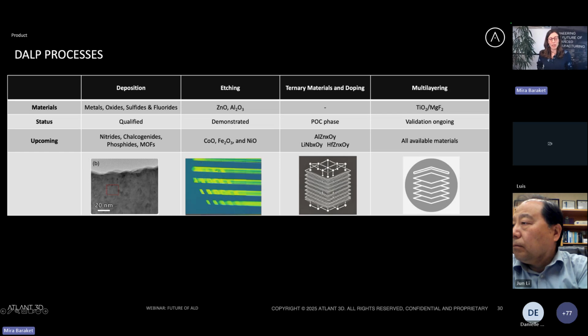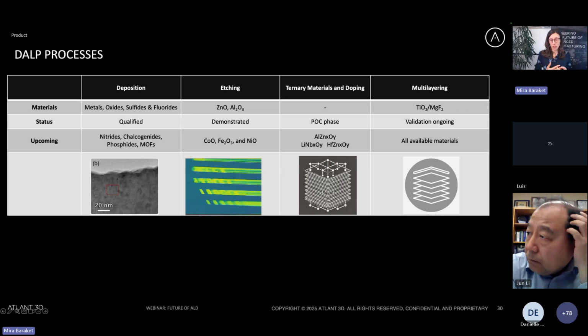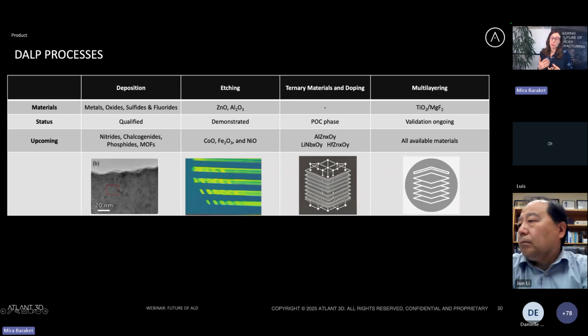Also on the etching side, we have confirmed and demonstrated etching of zinc oxide and aluminum oxide, and more are to come soon. We are in the proof of concept phase for making ternary materials, and we are interested in the materials that are listed here: aluminum zinc oxide, lithium niobium oxide, and hafnium zinc oxide. Multi-layering, of course, is inherent to our technology. So it is something that we can do with all available materials. We have already validated titanium oxide and magnesium fluoride, and also we've validated more materials that are based on aluminum, platinum, and others.